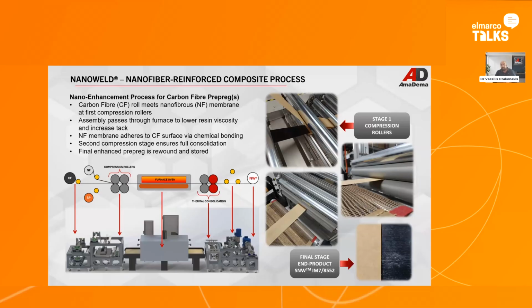What we have done, we have taken prepreg systems that are already in the market, that people or companies are familiar with, and for very specific nanofibers, we have made it so that we can process the prepreg and attach the nanofiber on it without losing the properties of the nanofiber and still have the nanofiber in the interlayer. Now, there is a difference between the two for those that understand composites, that when it comes to carbon fiber